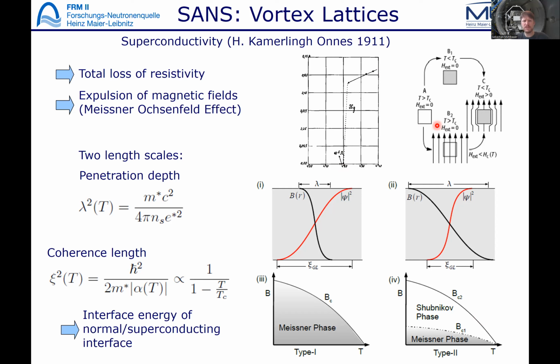If you put a superconductor into a magnetic field, the superconductivity is characterized by two length scales. One is the London penetration depth, which characterizes the scale on which a superconductor expels the magnetic field. And the second one is the coherence length, which is sort of the rigidity of the superconducting phase. And both of these length scales can be assigned to an energy or to a surface energy of a normal to superconducting interface.